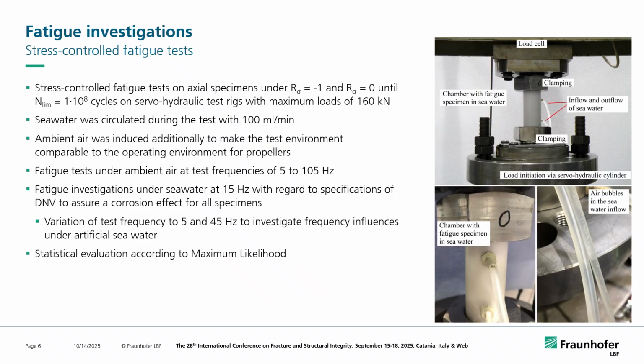Then we come to the fatigue tests. We went for stress-controlled fatigue tests under alternating loading and tensile loading. We made the tests mainly until 10 to the power 8 cycles on the servo-hydraulic test rig, which consumed a lot of time, to be honest, because the specimens are comparably large. So we went for a 16-ton machine, and on the other side, 10 to the power 8 is a large number of cycles. And we had to do so because we wanted to investigate the very high cycle fatigue range.